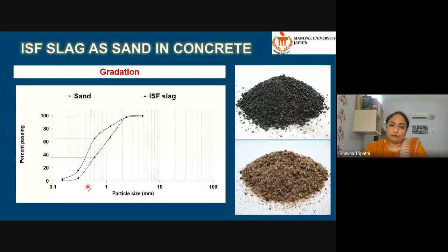Its conformation as zone 1 sand has enabled us to use this ISF slag in as received form. So the biggest advantage with ISF slag is that you can use it in as received form. There is no kind of processing used, and there is no requirement of sieving this. You can just procure ISF slag and use it as sand.